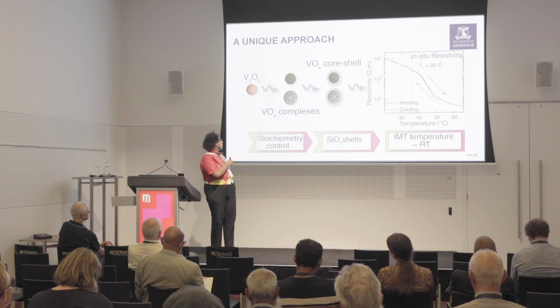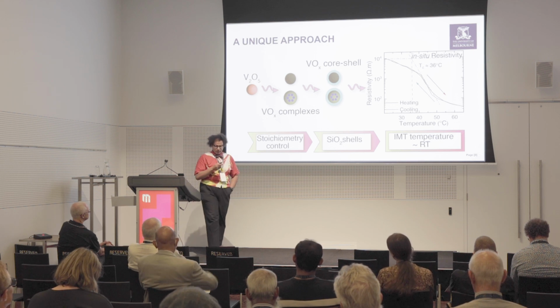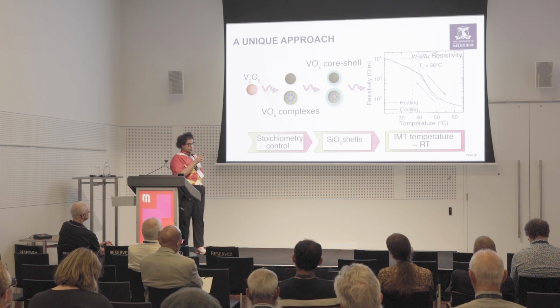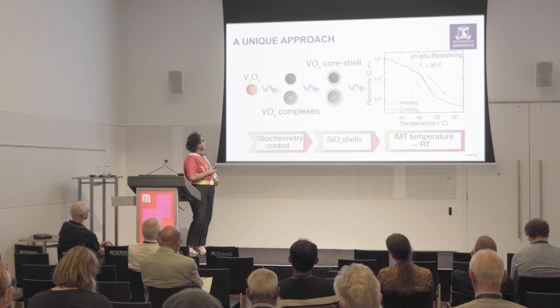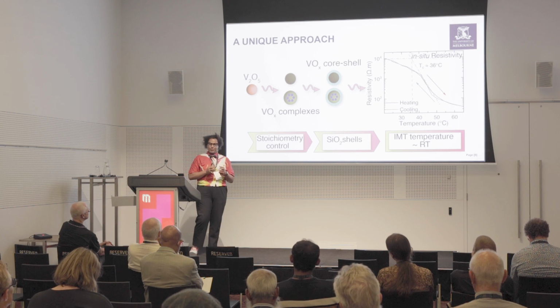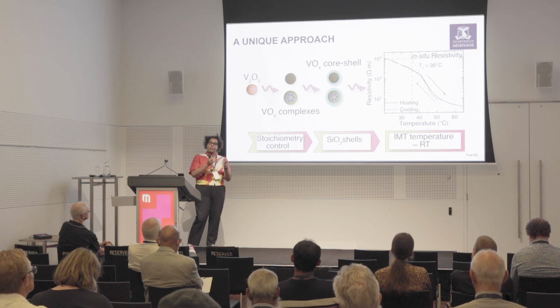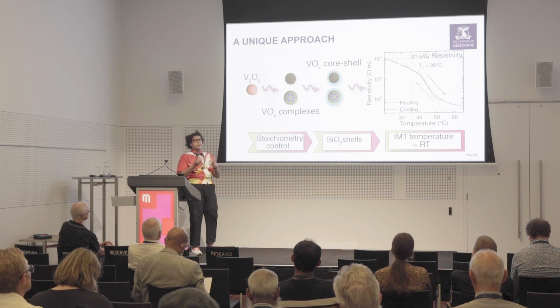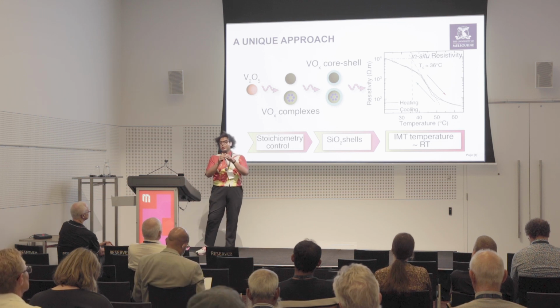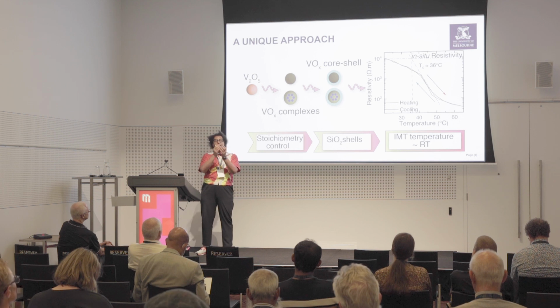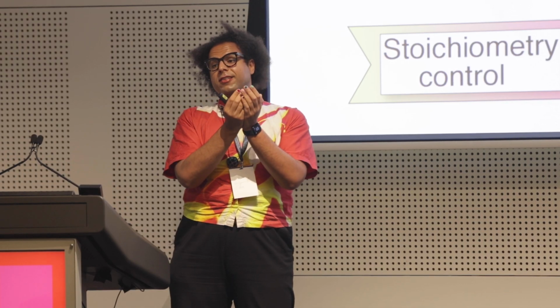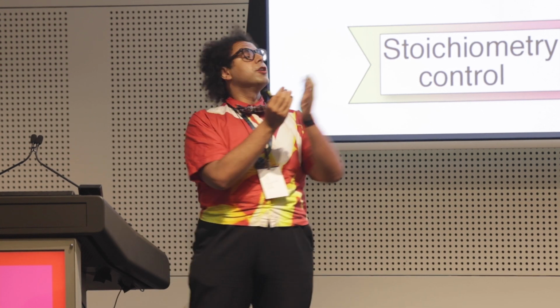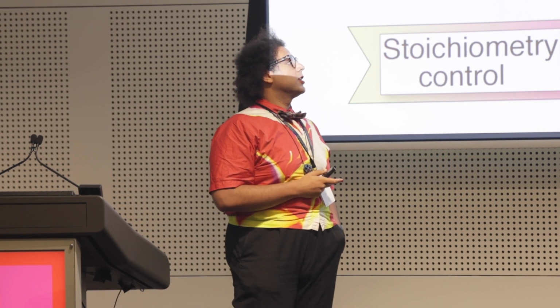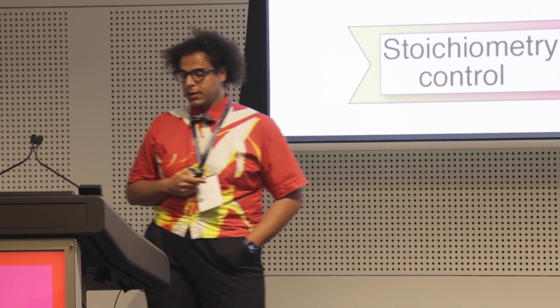But in our work, we purely work with two systems. We are looking at physical, intrinsic, and extrinsic strain. Intrinsic strain comes from stoichiometry, in which we control the stoichiometry, or how the compound is put together, and extrinsic strain in the form of silica shells. So we put the compound inside a glass sphere, and that glass sphere adds an extra pressure on the compound to drive it to change at that low temperature.